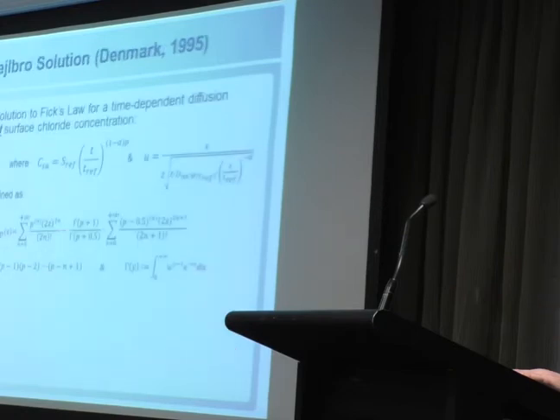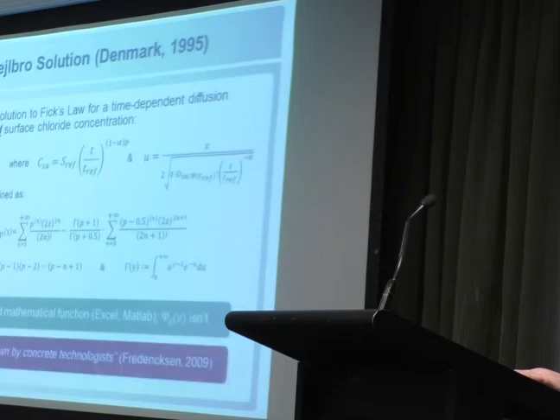that there is a generalized solution to Fick's law available, which allows for both a time-dependent diffusion coefficient and a surface chloride that's increasing with time. It's due to a Danish mathematician called Mejlbro. I guess it's not well known. It was described as not well known 15 years after it was first produced. I don't think anything has changed.